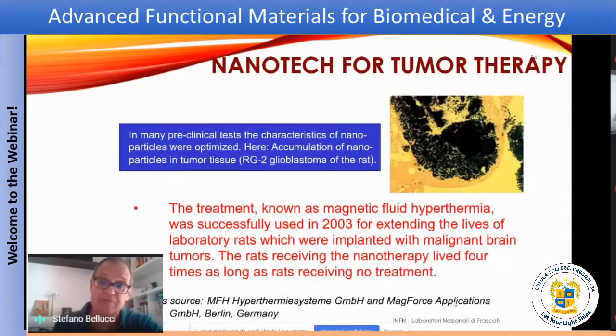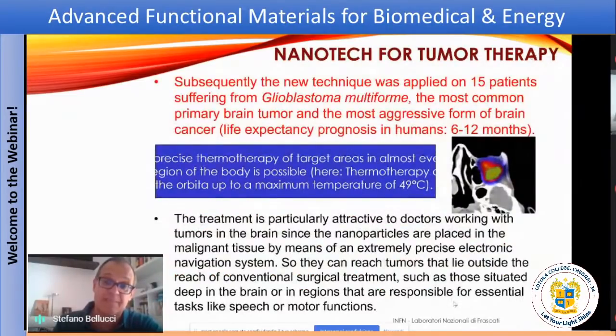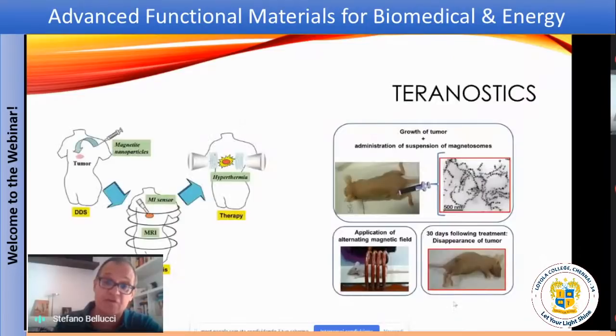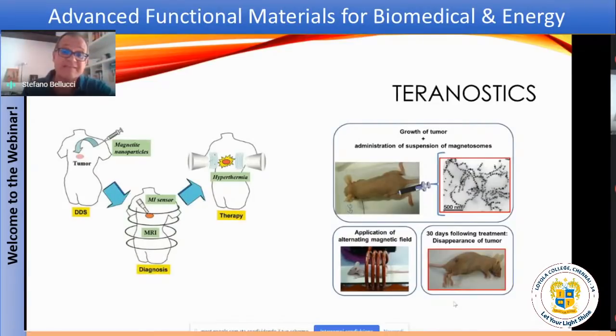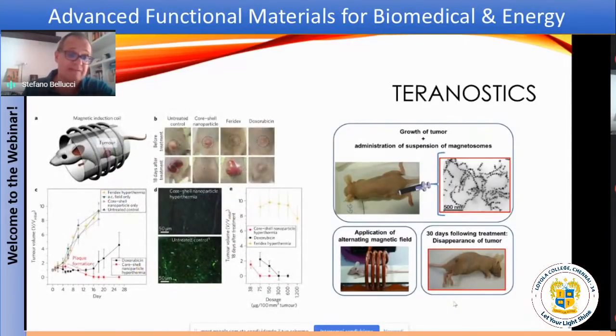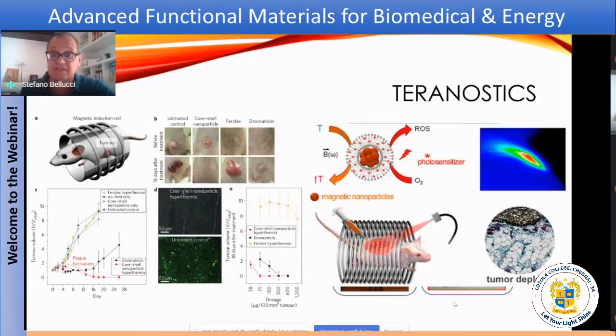And here you see examples on rat, and basically you see from the thermotherapy, the red spot is where in the eye orbita of the rat, where the tumor is being cured. So we have a tool for diagnostics, as I will show you in a minute, for imaging techniques and also for therapy. Combining them together, these magnetic nanoparticles can produce theranostics effects. And here you can observe and monitor the tumor, for instance, in this rat, which is put into a magnetic induction coil, and at the same time, the administration of these magnetosomes particles can cure the tumor, and you can observe the regression of tumor in real time. After 30 days, the disappearance of tumor is documented. That's the notion of theranostics. Magnetic nanoparticles, it's an example.